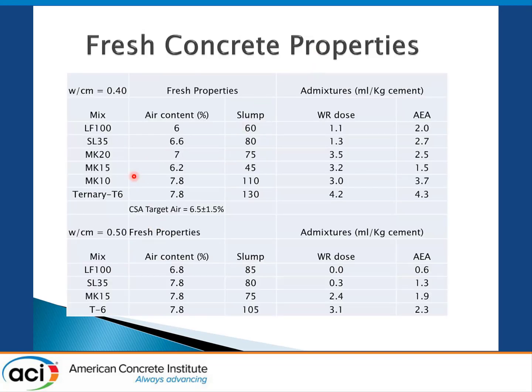For the fresh part, they're all air-entrained concretes because we live in a freeze-thaw environment in Canada. Our target air content is 6.5 plus or minus 1.5, and so these are all within that limit. There's some variability. The slump varied a bit at the top with the ternary mix and the 10% because we didn't have enough material to go back and repeat that. That may have been due to the higher polycarboxylate water reducer dose used in that study.